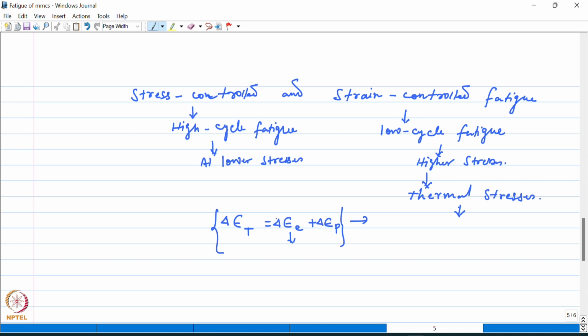The other thing that you should remember here is that in a composite material, the stresses and strains may not be uniform and the deformation can be highly localized as we have discussed. So it is important to differentiate between the average strains which represent the overall response of the composite and the local strains which arise due to the highly constrained deformation of the matrix due to the presence of the reinforcement. So when plotting the stress and strain, it may be a good idea to take the average strain, as you might have seen when we talked about the cyclic stress strain curves. We have actually considered the average strain along the x-axis.